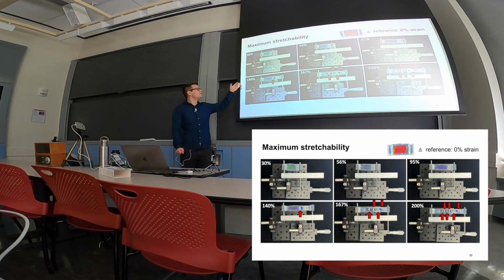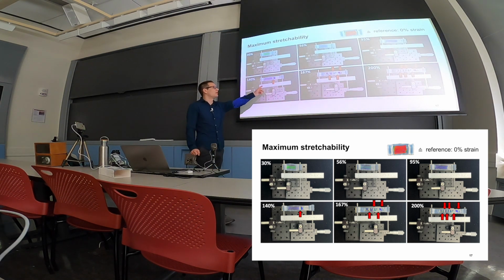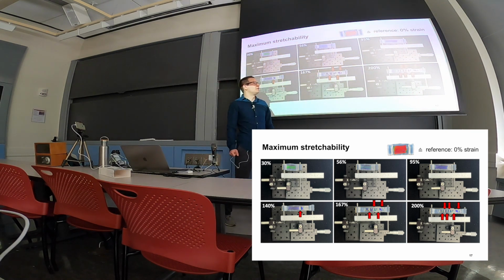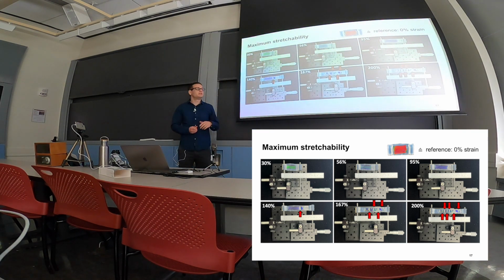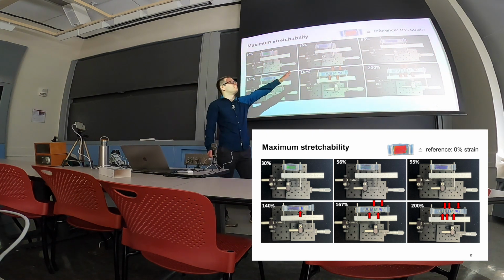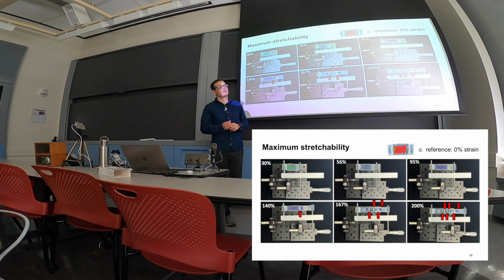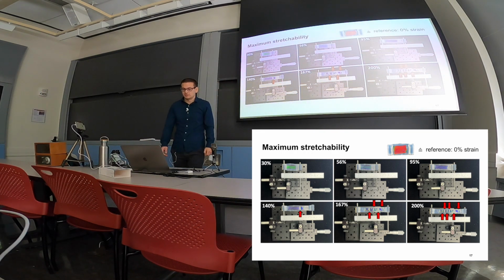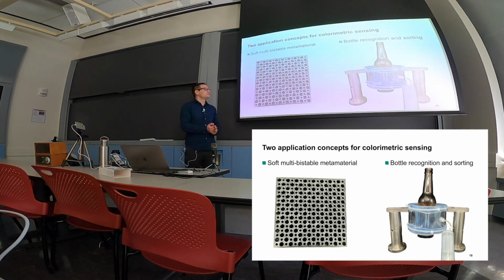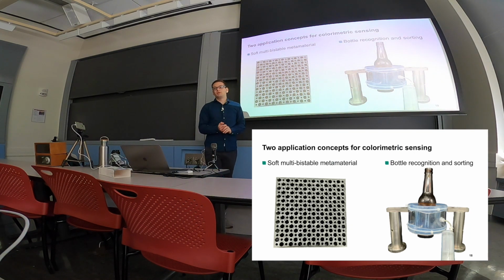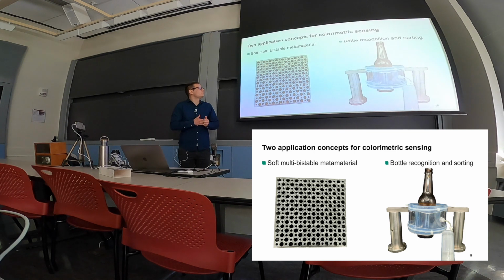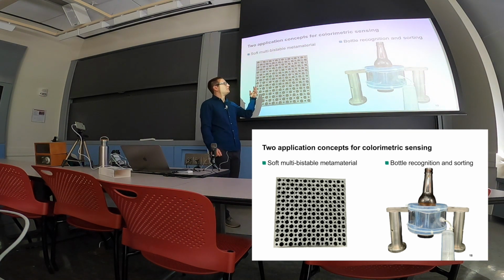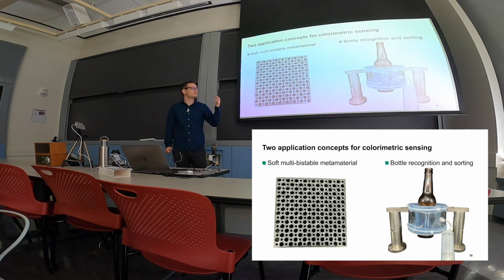But if we do so, we see at 140% the first tear occurring, and then of course if I stretch it more and more, more tears occur. So we should definitely not use it over 140%, but it is also not recommended to use it for more than 100%, because then we cannot sense anything with the system anymore. And now that I know the conditions under which I could use this material, and that it at least fulfills the points that have been mentioned in this progress report from 2018, I also wanted to realize 2 systems or 2 use cases where this material could give us an improvement.